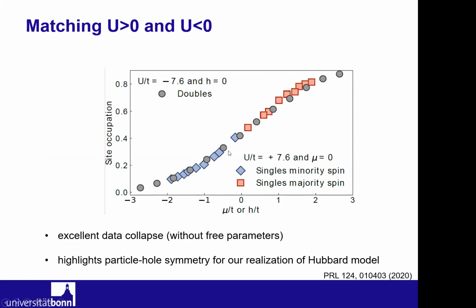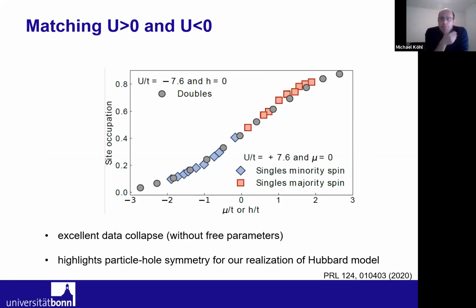And you see that these two curves collapse directly onto one another. There's no free parameters in there. Everything is just scaled in units of the tunneling matrix element, and we have a perfect collapse of the data. And this shows that for our realization of the Hubbard model, we really have a very good realization of this particle-hole symmetry.